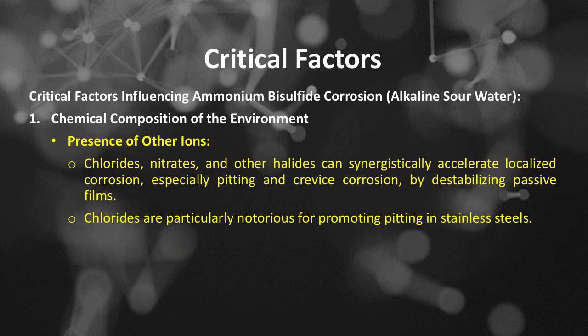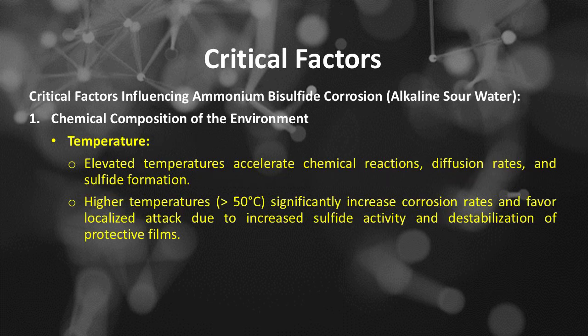The third is the presence of other ions. Chlorides, nitrates, and other halides can synergistically accelerate localized corrosion, especially pitting and crevice corrosion, by destabilizing passive films. Chlorides are particularly notorious for promoting pitting in stainless steels. The fourth is temperature. Elevated temperatures accelerate chemical reactions, diffusion rates, and sulfide formation. Higher temperatures, greater than 50 degrees Celsius, significantly increase corrosion rates and favor localized attack due to increased sulfide activity and destabilization of protective films.